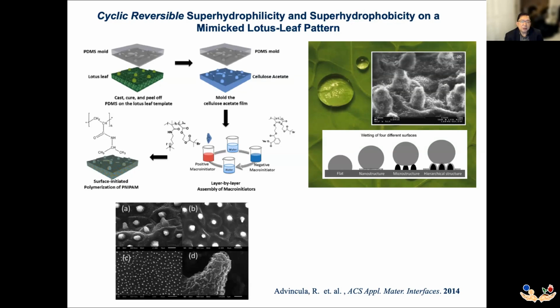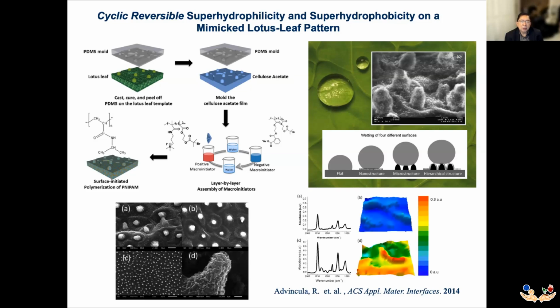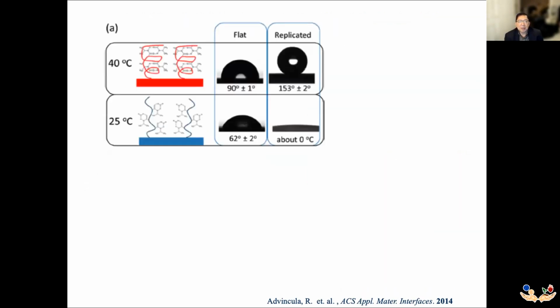This means that this artificially mimicked lotus leaf pattern actually has a chemistry that is based on the swelling behavior or the super hydrophobic to a super wetting switching that is dependent on the temperature. So what I mean by this is, as you can see here, a surface that is flat, not patterned, will give you, of course, some LCST behavior as shown here. When you heat the sample, you have a high wetting angle of 90, indicating hydrophobicity. On the other hand, cooling at 25 gives us a lower contact angle.